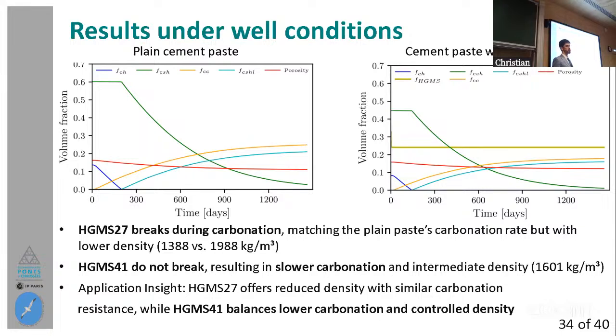Okay, let's now go to the cement paste with sphere 27. And there, well, it's not so easy to see, but we have some rupture of the spheres at the beginning when we apply the conditions, which resulted in this volume fraction of spheres being a little decreased. We increased the porosity a bit, but then it resulted the same as we obtained in the plain cement paste. So generally speaking, the diffusivity is the same, but we have less volume fraction of cement. So in this cement paste, the kinetics, or let's say the advance of the carbonation, was complete earlier than in the plain cement paste.